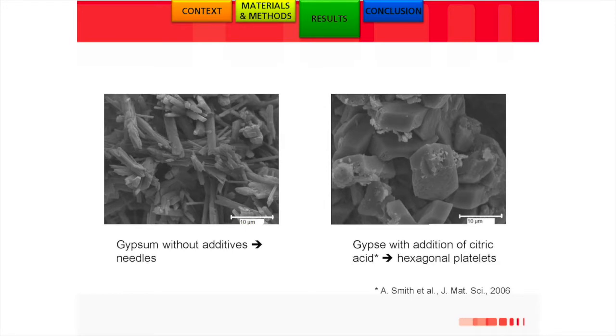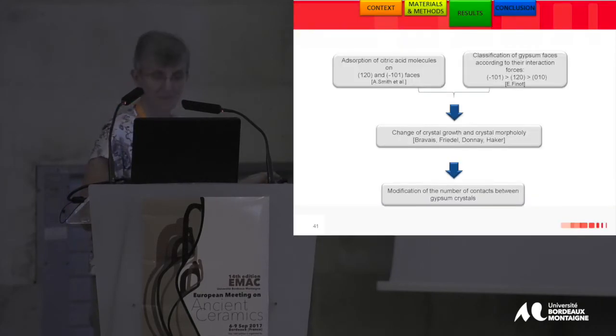How do we explain that? If we look at the microstructure of gypsum without additive, we have a needle-like structure. With an addition of citric acid in very small quantity, we obtain platelets. Why do we have this morphology? Because we showed that the molecules of the citric acid adsorbed on specific gypsum faces, 1,2,0 and minus 1,0,1, which were found to be the most reactive faces.